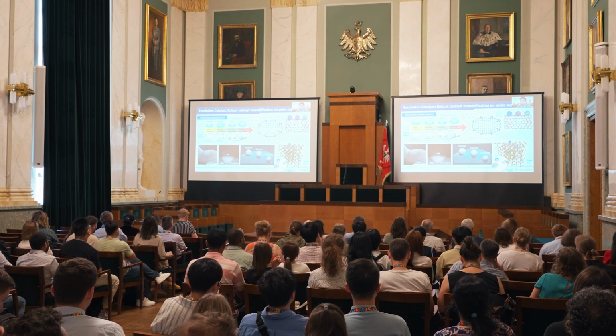On the other hand, there is exsolution starting from doping. You can see this is the perovskite structure, with B-site doped element. With reducing atmosphere and high temperature annealing, this dopant element is extruded, then segregated on this oxide support layer, forming these exsolved catalyst structures. The main advantage of this exsolution is that you can see a socketed structure. That's why we can see high mechanical and high thermal stability when we use these exsolution catalyst particles.